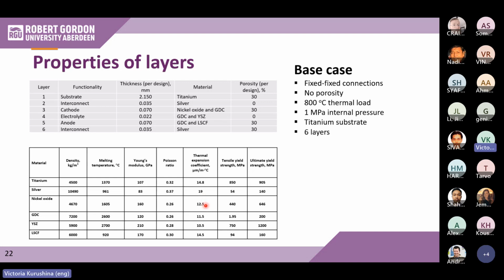Also, the base case thermomechanical test that I'm going to show assumes the worst case conditions, where both ends of the cell are fixed and there is no porosity in the layers. This will allow us to obtain the maximum thermal expansion. So this is really a worst case scenario. It comes from the density, which is considered at its maximum, basically.